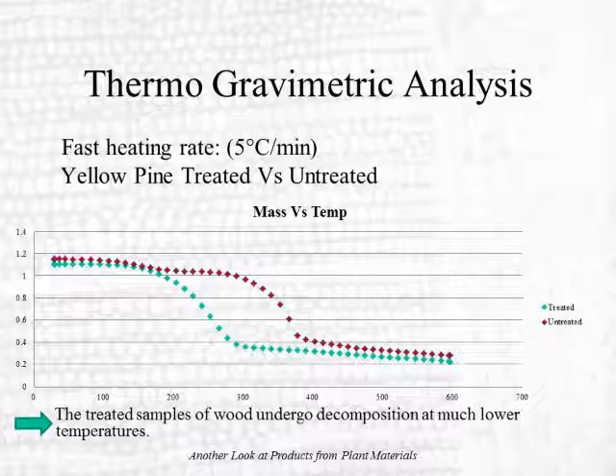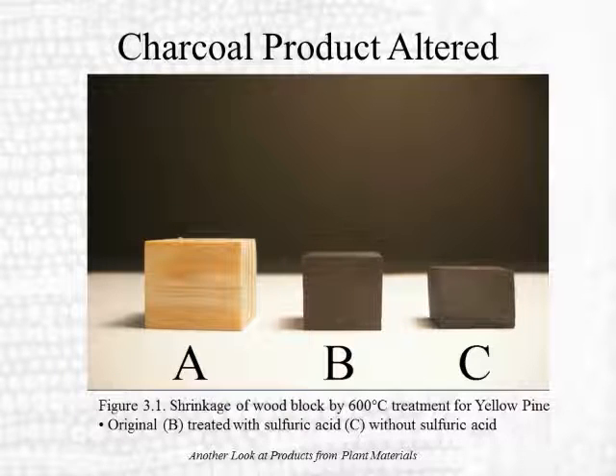So we have different temperatures required when treating it to get this kind of decomposition, and we got greater mass, or greater amounts of charcoal, when we did the pretreatment. Just as a picture to emphasize the influence on the solid product from carbonization, you go from a wood block to a charcoal block, this one having been pretreated and heated to 600 degrees centigrade. One that wasn't pretreated and heated to 600 degrees centigrade. Clearly there are dimensional changes that occur, and with pretreatment we alter the dimensional changes and the mass yield.